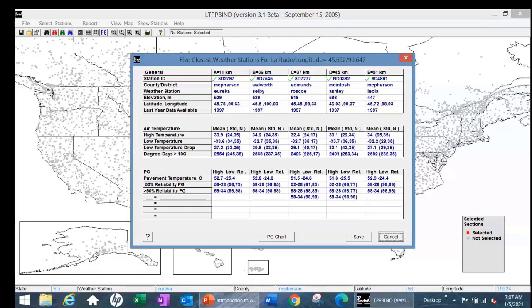And for those 5 stations, it gives you the average and the deviation of the high temperature and low temperature. Also the temperature drop, how fast the temperature drops. And for those of you that are still using concrete, strictly in structural concrete for bridges and stuff, it gives you degree days too. But the bottom third of that is what we're looking for.